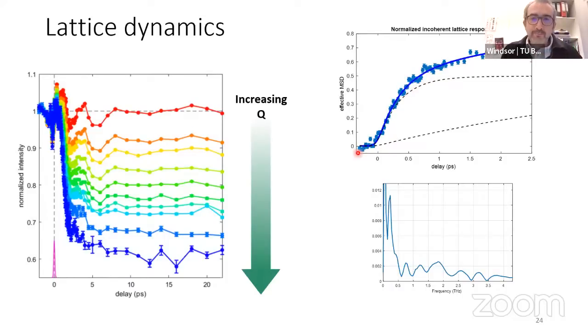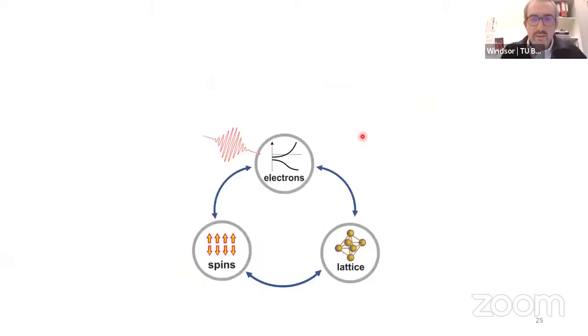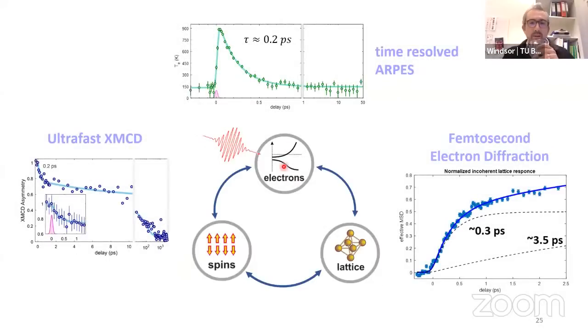This is a graph that shows us how the incoherent vibrations of atoms rise following the photoexcitation. And we see that we have two timescales here. Again, an initial very fast sub-picosecond timescale, similar to what we saw before, and another longer timescale. And I want to first finish our initial stamp collection and then come back to this. So what we've done is we've looked at all three degrees of freedom, and we've collected data from each one of them.